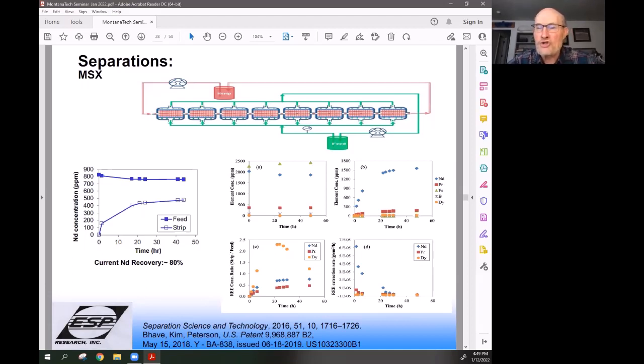These do require clean streams. You have to have a fairly well filtered stream before it goes in, so there's not a lot of particulates hitting the membrane, for 2 reasons. 1, the particulates will get stuck on the membrane and foul it. And 2, if you're using high face velocities, which this requires, they'll tend to erode the surface of the membrane, destroy its selectivity, and release the organic. So there are some tricks to how you run these, but you can run these and they do work very efficiently. And this process is being licensed by a couple of different mining companies right now. Next, please.